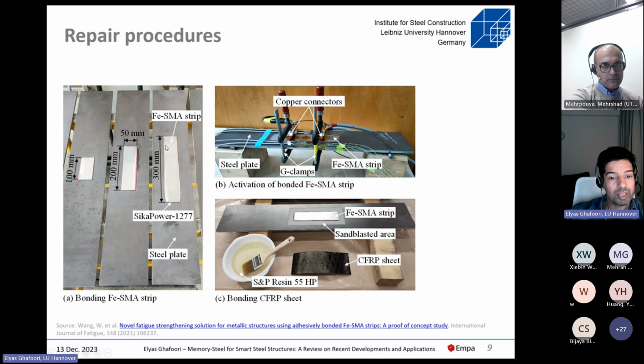We have a few different PhD students. You can see also some of our publications here, where they are trying different types of patches, small patches as small as your palm. So you can apply them really quickly on the area where there is a crack, let it cure, and then heat it with different methods, whatever method is more convenient. We could actually apply also CFRP, carbon fiber reinforced polymer sheets, on top of that.